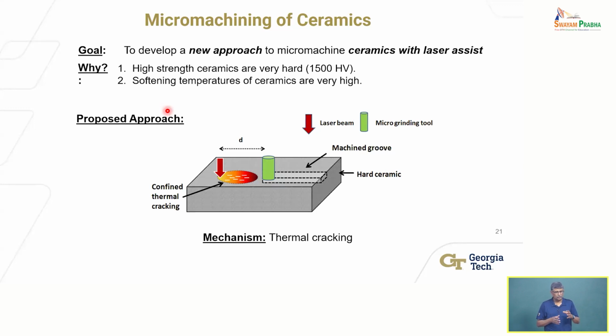But I want to do controlled fracture. I don't want to fracture the whole thing. Then that defeats the whole purpose. So I will irradiate with a laser, right? And generate very rapidly, because laser heating is very rapid heating and rapid cooling, right? When the laser moves away, you actually generate thermal stresses. Instantaneously generate very high thermal stresses, localized by controlling the process, the laser irradiation characteristics.